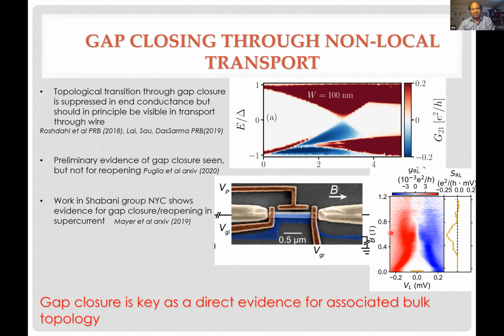Unfortunately, this experiment was also done, it just appeared on the arXiv this year, so it's very new. And this shows a bulk gap closing, which is encouraging, but not much of a reopening. And that's disappointing. So actually, incidentally, your neighbors, the Javad Shabani group at NYU, found some supercurrent closing and reopening for the same kind of physics. But again, we're still trying to understand this.